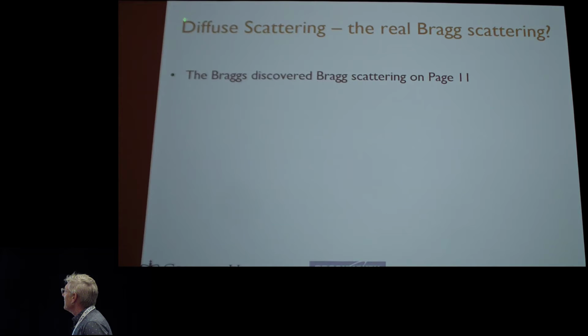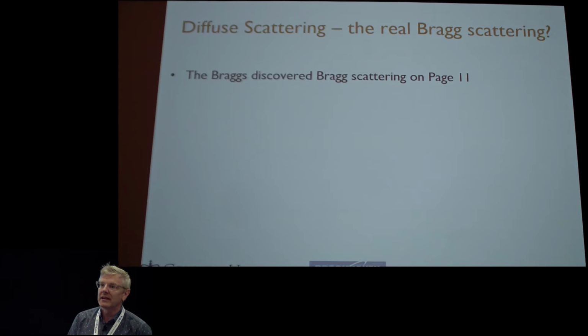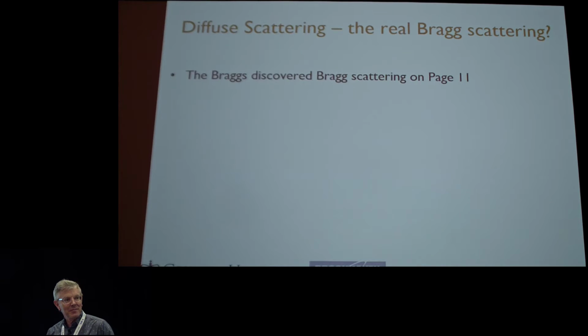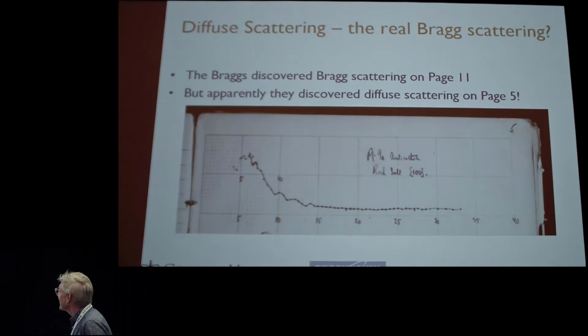Okay, so I showed you a little bit earlier that on page 11 of Bragg's notebook, they discovered the world's first Bragg peak. But I just want to tell you that actually the most interesting scattering, as I've been telling you, is not the Bragg peaks, it's the diffuse scattering underneath the Bragg peaks. And it turns out that they discovered diffuse scattering on page 5. So the real Bragg scattering is diffuse scattering, in my opinion.